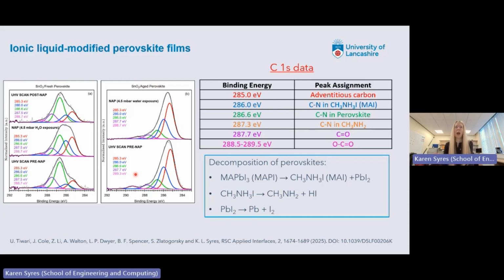So again, I'm not going to tell you what every peak here means, but we've got two samples. One is a very fresh perovskite film. So this is just pure perovskite to start with, without the ionic liquids. We literally deposited it and put it straight into the experiment. And then we've got what we call an aged one, which was about a week old. We made it about a week before, and we did store it in very careful conditions under a nitrogen environment. But as we will see, it is heavily degraded after just a week.